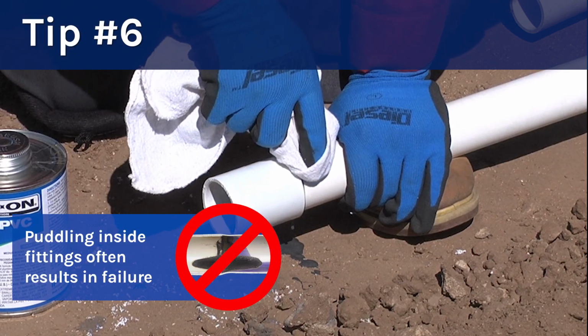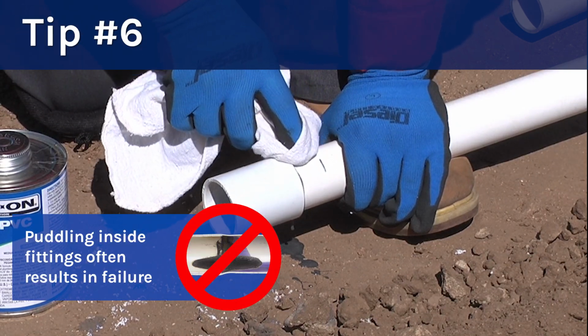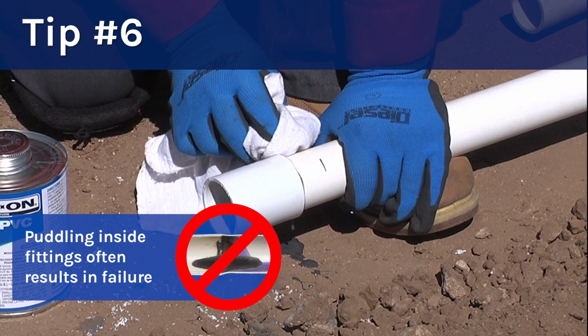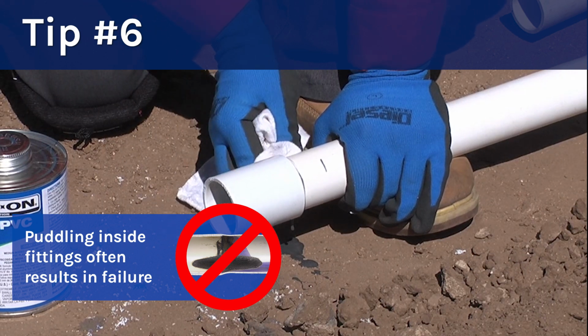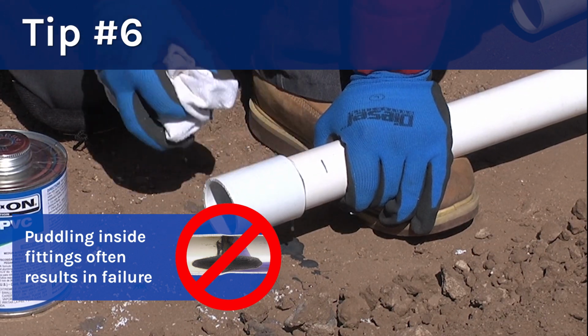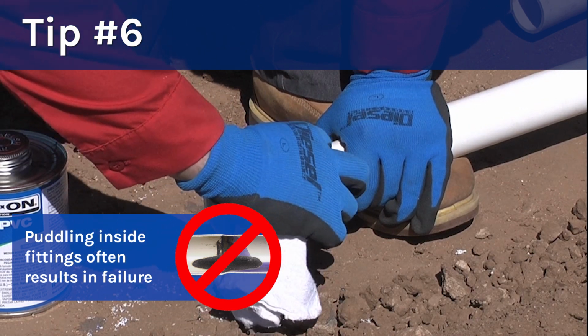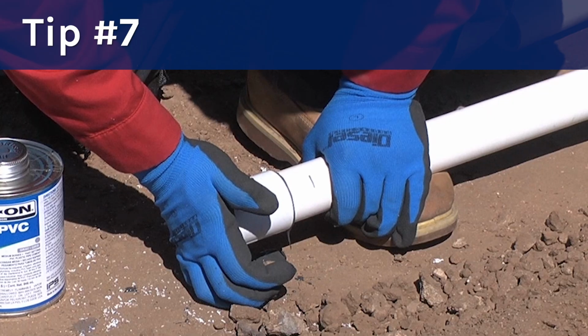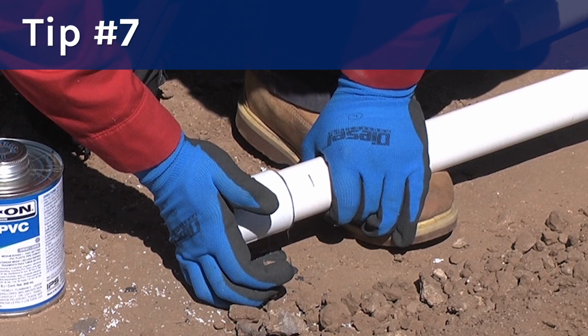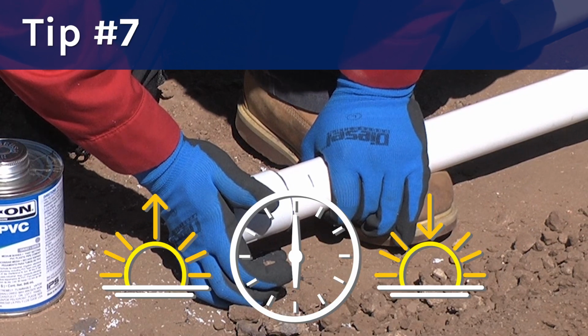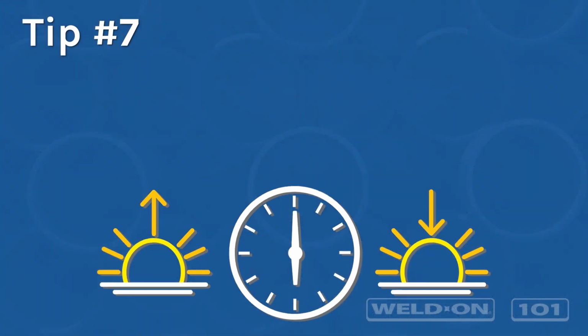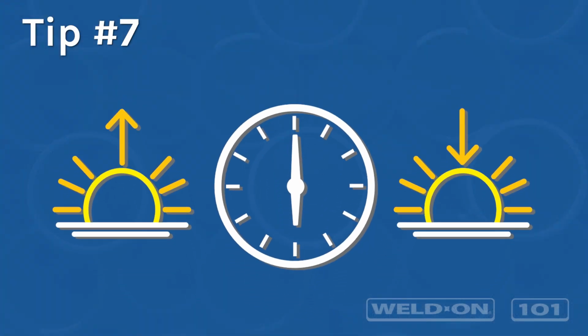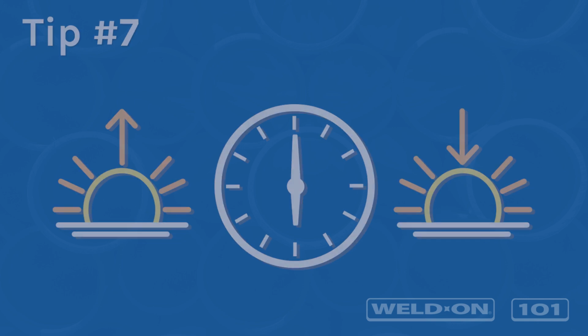Chemical solvents attack hot surfaces faster and deeper, especially inside a joint. Therefore, it is very important to avoid puddling the solvent cement inside the fitting socket and to wipe off any excess solvent cement outside the joint. Anchored and final connections should be made during the cooler hours of the day when possible. There can be a greater expansion-contraction factor affecting the pipe in hot weather. We suggest you follow the advice of the pipe manufacturer regarding this condition.